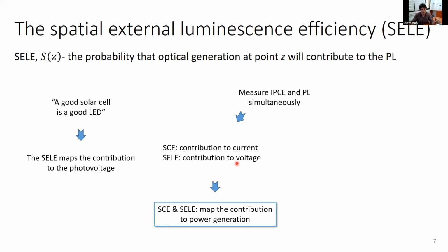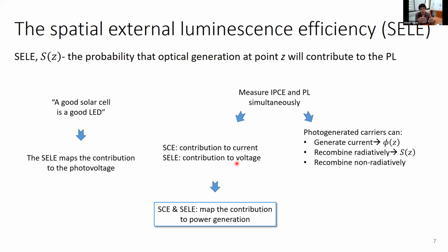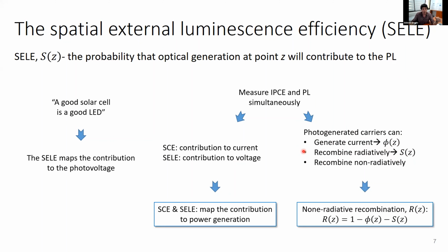This is on one side. On the other side, if we look at all the different things that can happen to charge carriers, they can be generated as current. Well, we map these with the spatial collection efficiency. They can recombine radiatively. We just talked about how we map these. Besides those, they can only recombine non-radiatively. So all in all, if we can map 2 out of the 3, we can actually find the third. So by doing the SELE analysis and the spatial collection efficiency analysis, we can get a complete functional mapping of everything that's happening inside the device.